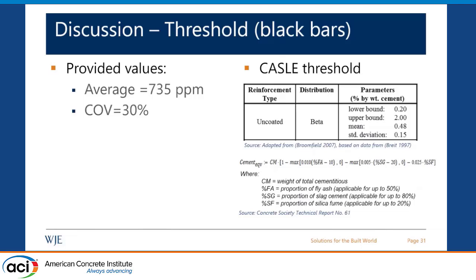And we recognize that the chloride threshold is affected by your mixed design, so the cement content and if you have supplementary cementitious material. And the approach that we've taken to consider that is similar to what is presented in Concrete Society TR 61. So it takes into consideration how fly ash and slag can reduce the hydroxyl ions in your concrete as they react with the hydration products and affect what we call effective cement content. And this is what we use to come up with the chloride threshold.